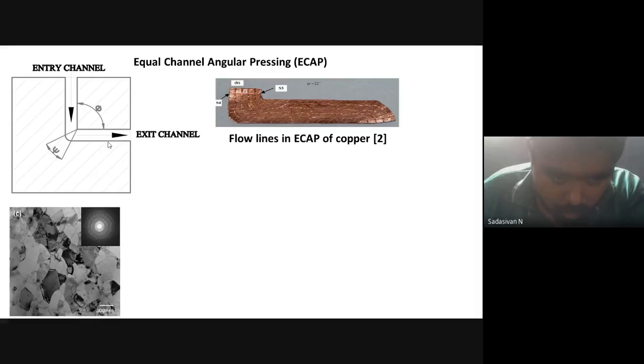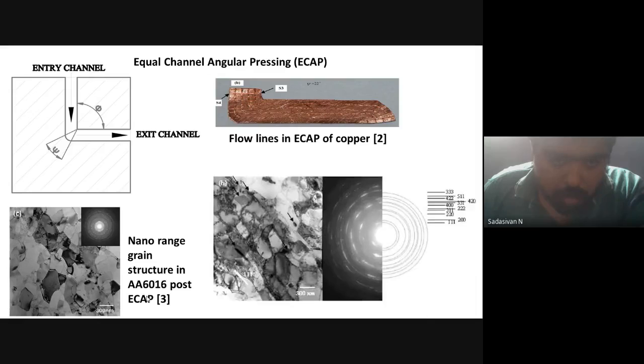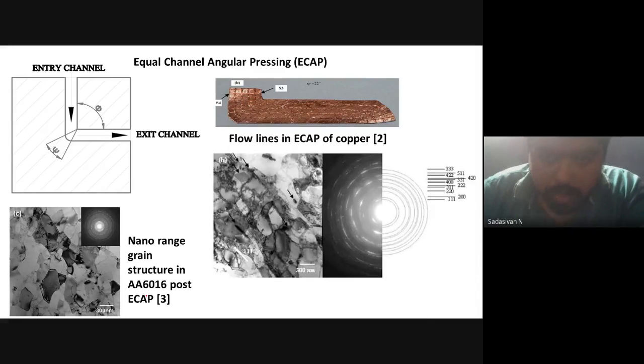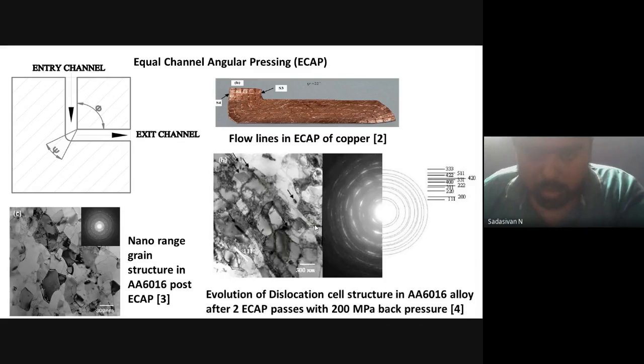So it gives us a nano range grain structure with considerable effect in 3 to 4 passes. We can go to the nano range of grain size, which gives substantially high mechanical properties. But the problem is you always lose ductility. In the image, you can see the pileup of dislocations near the boundaries and subgrains forming. If we keep processing through multiple passes, these subgrains in turn become individual grains, and that is the mechanism of grain refinement. All these dislocations that get piled up add to your strength. So that is grain boundary strengthening.